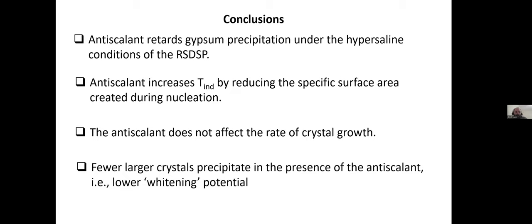So just to conclude this part of the talk, the antiscalants do work under the hypersaline conditions of the RSDSP. They impact the induction time, and through affecting the specific surface area created during the nucleation, they do not impact the crystal growth rate. And one thing we did see is that the addition of scale inhibitors creates fewer larger crystals, which for whitening event potential is great. However, as I mentioned earlier, we should also consider possible implications for the biota in the lake once we start adding seawater inside and lowering the salinity.